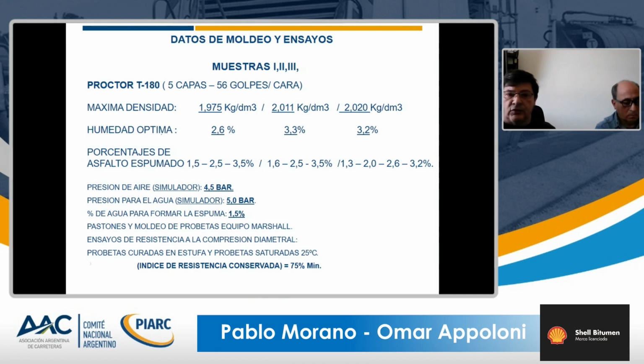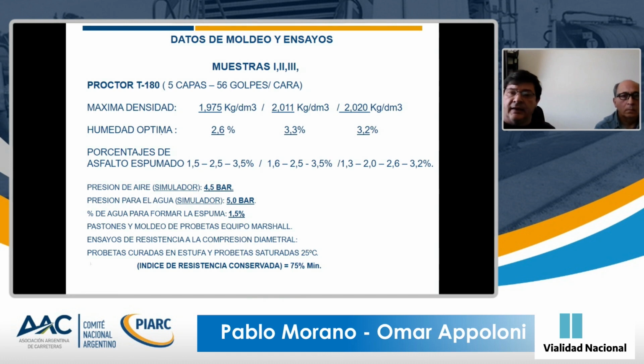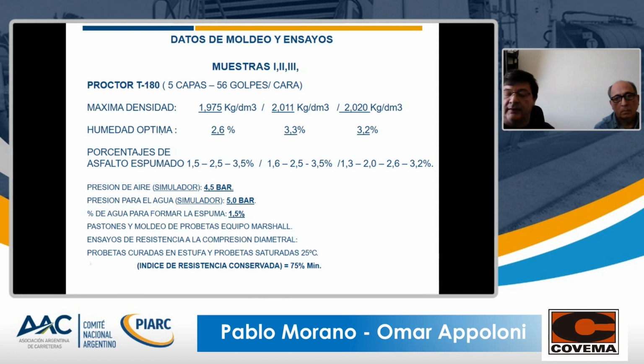With the simulator, in order to get the foam that we were looking for, the air pressure in the simulator was 4.5 bars, and the water pressure injection was 5.0 bars. The percentage of water for the foam was 1.5%, and then